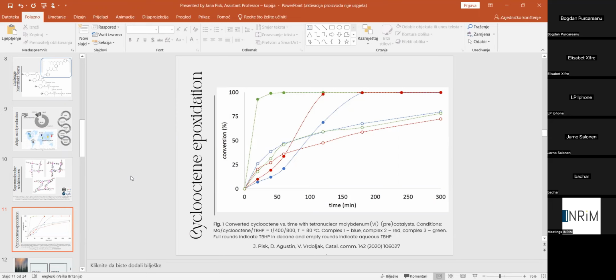Those are the results that are presented in full colored dots. As you can see on those slides, we found 3 very good catalysts that are quite active after a short time of the reaction. The catalyst presented here with the green lines is very highly active after only 20 minutes of the reaction. The other 2 catalysts are also active, but they need some time to get activated, which is called induction time. All other catalysts using TBHP in water as oxidant show less activity, but when comparing with other literature results, it is quite good also.